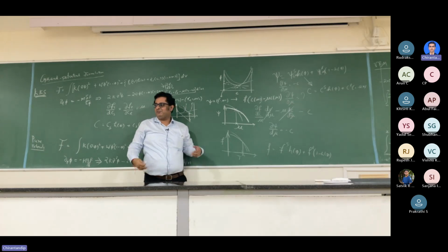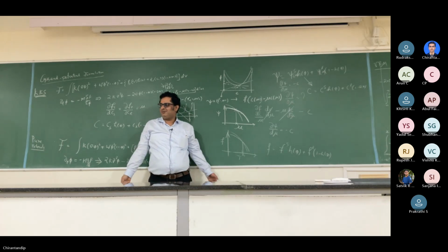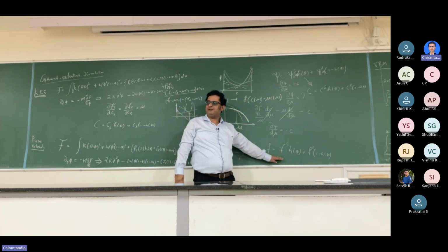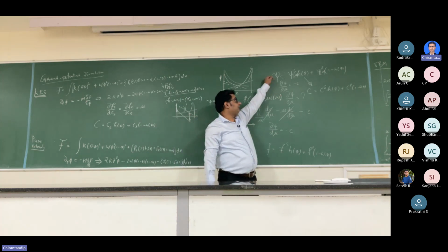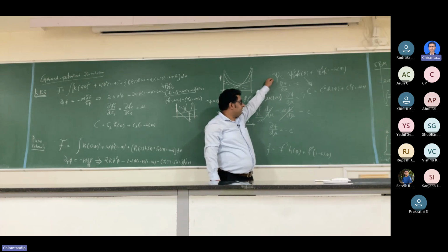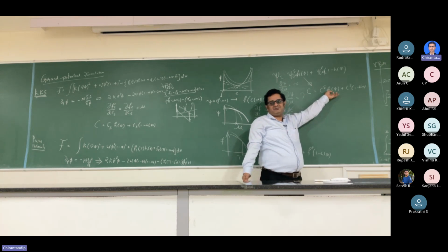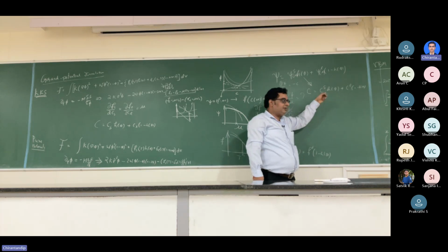Okay. So it is basically following from what we started yesterday, of what we formulate as the free energy formulation, right? Or you constructed a potential of this type, which upon differentiation with respect to the dependent variable gives you something like this, which is the constraint that we use in the KKS model as an arbitrary condition. Now this follows from the thermodynamics. Correct. Alright, it's not arbitrary. It has to be. Alright.